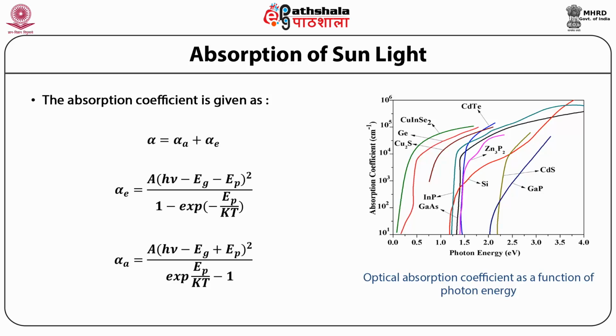Therefore, in a thin material, the homojunction should have a very small depth from the surface so that light can penetrate into the junction. Hence, the direct band gap material homojunction gives higher recombination, or basically the surface recombination losses. However, some of the problems are overcome by using a heterojunction structure of larger band gap material on the direct band gap absorbing material.